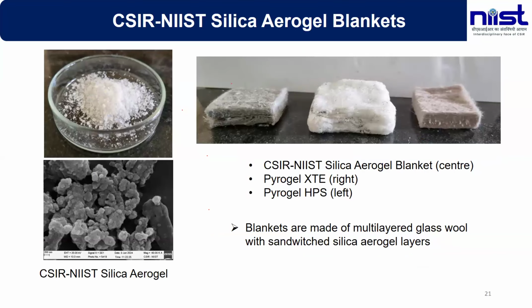And we bought an aerogel blanket from industry, so that it will be the benchmark, and we can also make products similar to that. The aerogels are embedded in a glass wool matrix. And glass wool, as you know, is an excellent low thermal conducting thermal insulation blanket, which has a temperature stability of up to 600 degrees Celsius. So this aerogel was introduced in the blanket, and we have also studied some of the applications in line with these results.